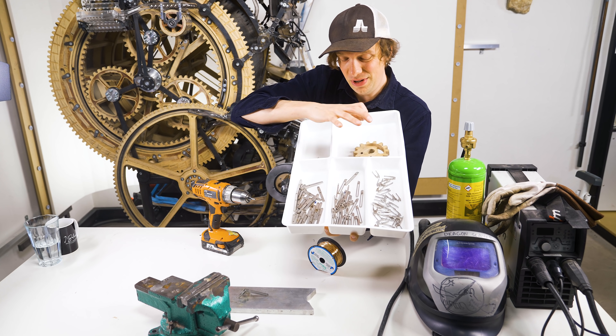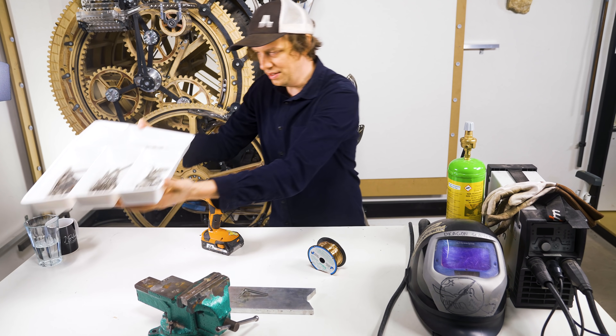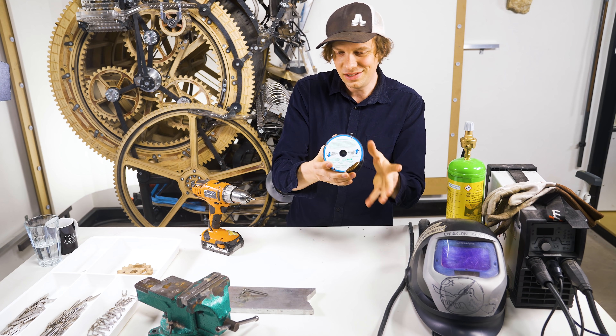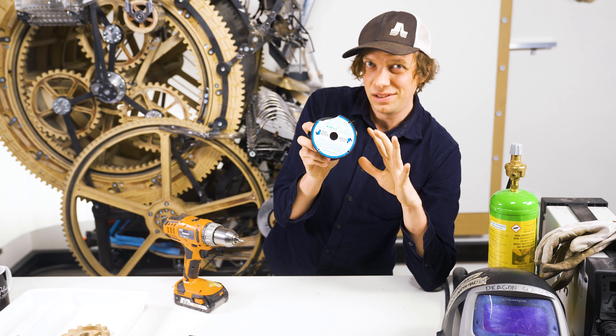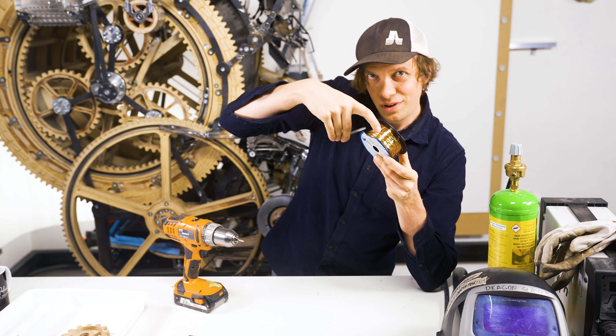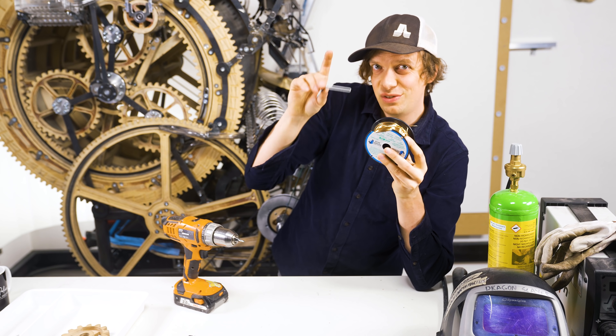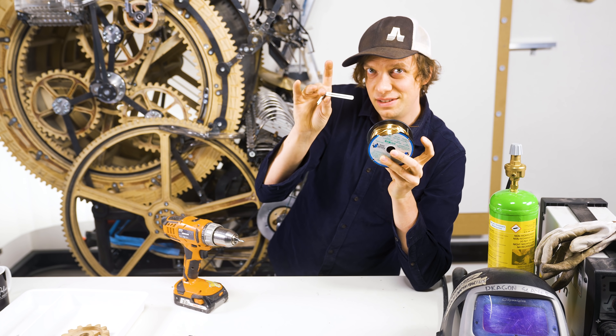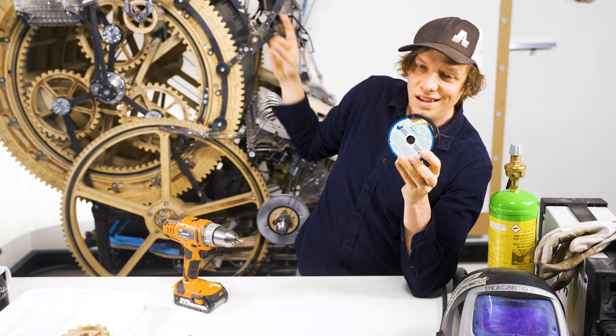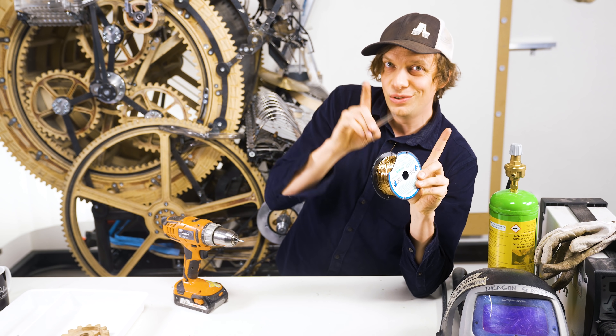All these parts are cut loose and ready for welding. Since this is stainless steel and very thin and small, I need to think about how to weld this. I'm actually going to use silicon bronze TIG brazing — so it's not technically welding. Silicon bronze TIG brazing has a lower melting temperature, which means I don't need to melt these small parts before the filler material melts and bonds them together. Also, my normal filler rods are for mild steel and you shouldn't blend stainless steel with mild steel. By the end of the process I'll weld the stainless dropper arms to mild steel arms on the Marble Machine X, and that's the best example of where silicon bronze TIG brazing comes in because it can weld different alloys to each other.